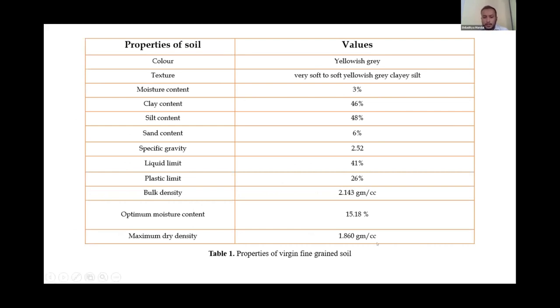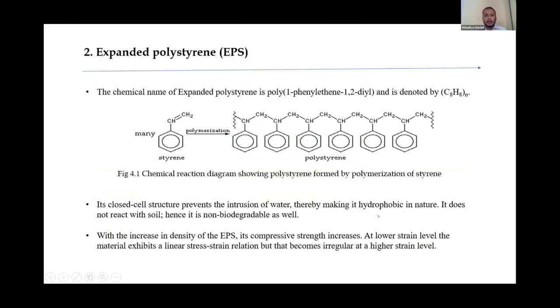And this is the MDD value, and this is the corresponding OMC of the virgin soil. And now our second material, which is to be used for stabilization, is nothing but polystyrene. As you can see, styrene after polymerization converts into polystyrene, which is a very closed chain network. That signifies that when it's a closed chain network, it can be hydrophobic in nature, that means water repelling in nature. And since it's hydrophobic, it does not react with soil and is non-biodegradable as well.